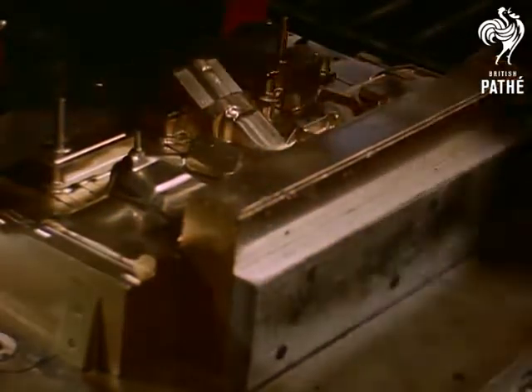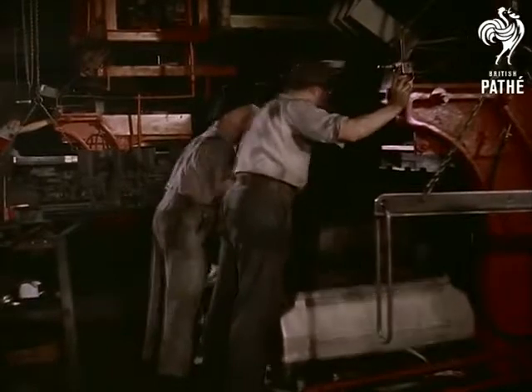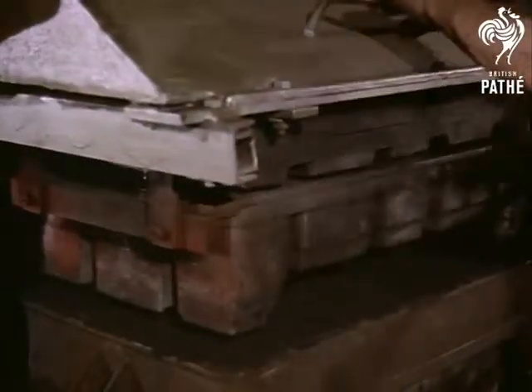A mold is now prepared for one of the 2 halves of the cylinder block. Over the pattern, which is accurately made, is placed a molding box, and they are securely clamped together. A mixture of moist sand, clay, and coal dust is poured onto the pattern while it is on a jolting machine. The vigorous action of the jolt machine shakes the sand into the crevices of the pattern until the pneumatic ram on the head of the machine descends and the sand is squeezed under tremendous pressure into a firm mass.